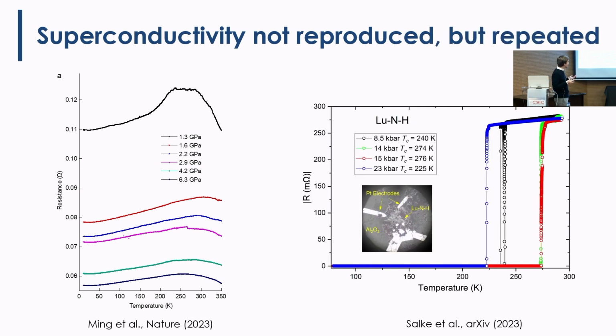But there is this claim, this is a bit mysterious, that the paper of Russ Hemley in Chicago, Russ Hemley is a very well-reputed scientist in the high pressure community, that he apparently got Dias's sample, they take it to Chicago from Rochester, and repeat the resistivity measurements, and they claim here there is no background subtraction again, and you see that it's 0. I don't know. So it's the same sample, okay? But they repeat the resistivity.